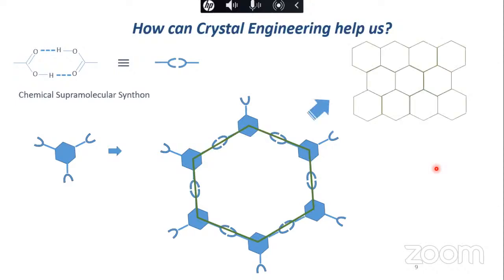Then, for example, in this case, if we have these hexagons, then you will basically form something like this. And so these hexagons, you are going to extend each one. For example, here you have a molecule, and it is extended in 3 dimensions. So you get a hexagonal array. If you have a big void, either you will have solvent here, if it is a flat layer, or these layers can interpenetrate and then form more complex structures. Then when they pack in 3 dimensions, you get a crystal structure.